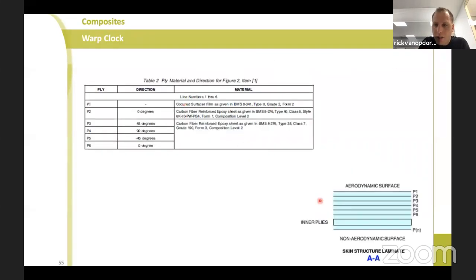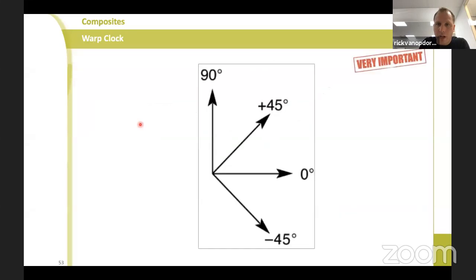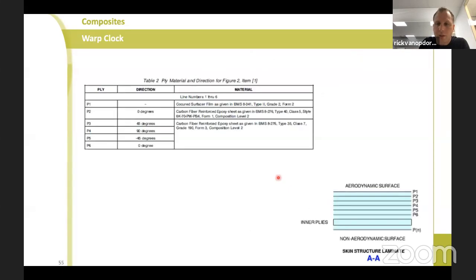So this is a copy of the structural repair manual from Boeing. And what you see here is a panel, and this panel is built up out of ply one. P stands for ply: P1, P2, P3, P4, and so on. And then you see 0 degree, 45 degree, 90 degree. You see the material it's made from. So now I know my panel is built up out of six layers, six plies, and ply two is 0 degree, ply three is 45 degree. So I know that ply one is this direction, ply two is this direction. It's very important information to identify the material.